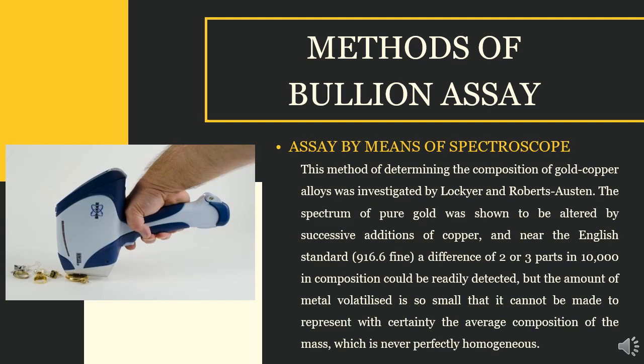Lastly, assay by means of the spectroscope. This method of determining the composition of gold-copper alloys was investigated by Lockyer and Roberts-Austen. The spectrum of pure gold was shown to be altered by successive additions of copper, and near the English standard, 916.6 fine, a difference of 2 or 3 parts in 10,000 in composition could be readily detected, but the amount of metal volatilized is so small that it could not be made to represent with certainty the average composition of the mass, which is never perfectly homogeneous.